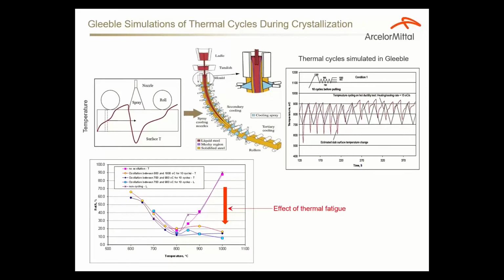There's another aspect: when the steel is being cast, the mold is continuously cooled, and the steel is continuously cooled by water spraying onto the surface. So the surface temperature basically changes as the steel travels through the caster. So the surface temperature oscillates like this, and this can facilitate cracking as well. The Gleeble machine, with its high flexibility and temperature control, allows us to simulate this kind of thermal cycling on the surface, and then we perform ductility tests, and we show that this thermal fatigue, very low cycle thermal fatigue, can contribute to ductility loss.